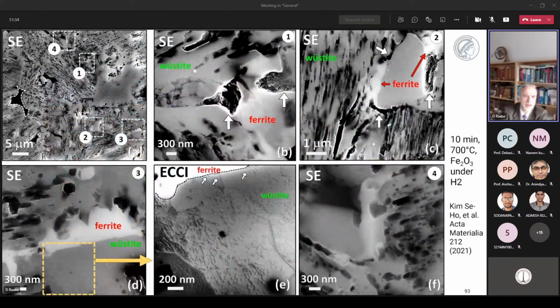When you magnify and look a little bit into the microstructure after 10 minutes, you see that much of the iron has already formed. You see, however, when we go into these 4 different snapshots, that yes, you have a couple of ferritic regions which are surrounding part of the wüstite, and the last stage oxide is the wüstite, the FeO. But you see it's not entirely wrapped. There are areas which I highlight here that indeed have a delamination or crack, which is very important to understand because the high temperature mechanics play a very big role here.